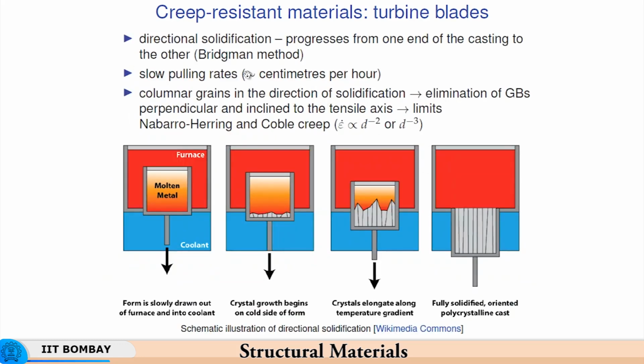So, if one wants to make turbine blades creep resistant material by directional solidification, one needs to have molten material in the furnace, and you see that the form is slowly drawn out of the furnace into the coolant. So, slowly the form gets drawn into the coolant, and you have progressively directionally solidified material.